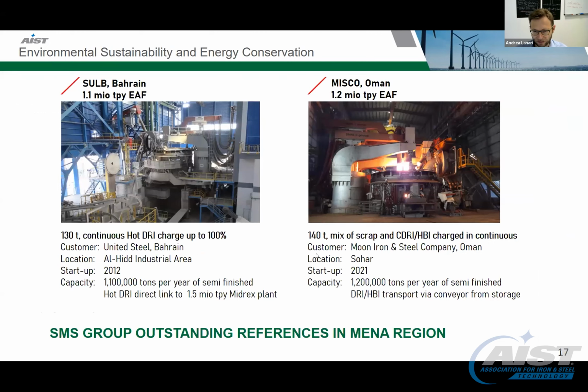As SMS, of course, we have been active already in DRI plants. We are just going to mention two references already existing and running, one in Bahrain, in Sulb. We are talking about a 130-ton electrical furnace, running with 100% constant, of course, hot DRI. Hot DRI, the temperature 560, 570 degrees Celsius at the input of the electrical furnace. This has been in operation for almost 7 years. Yes, 7 years. The second reference, which is already installed and is now starting commercial production, is in Oman for 1.2 million. In this case, this is working with HBI.